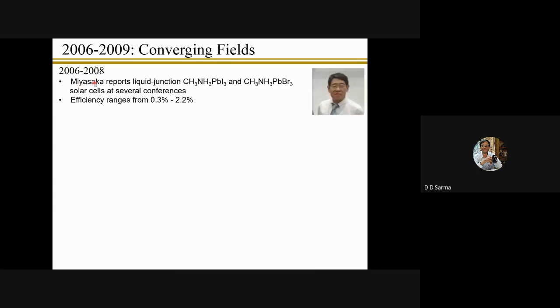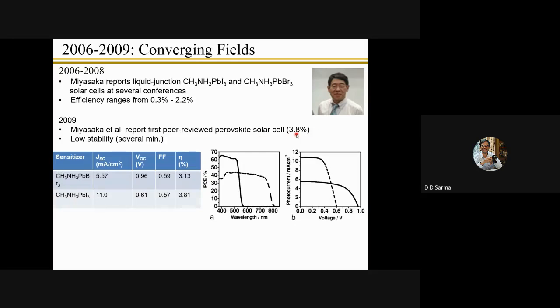A little bit of history of this material. This was originally researched by Miyasaka in 2006 to 2008, and nobody took interest in it because the efficiency that he found was very small. Not only was it very small, he even showed a 4% efficiency, but it was extremely unstable. In several minutes, the efficiency was gone.